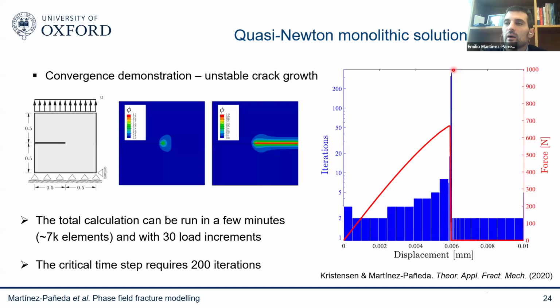So it's something, I would say, relatively unique to the phase field in the sense that by isolating the phase field, the damage variable, from the displacement field, you gain this additional robustness. Even though you need 200 iterations here, the total number of increments and iterations is very small. So I can run this simulation, an unstable fracture event, on my laptop in, I would say, seconds, maybe a few minutes, let's say 1-2 minutes. So it's very, very fast, and this is the beauty of it.